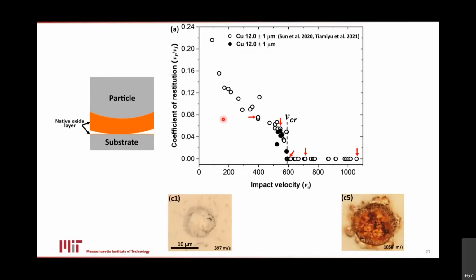Now let's go to the other side of this diagram. Here's what it looks like if I do this impact, but the particle bounces away and I've just dented the substrate. You can see we've made a crater, but we haven't got any change in the oxide. It's just a clean, well-prepared substrate; there's no oxide going on. So this is full oxide, this is no oxide. Now we can go to the region in the middle and start to explore it. In between, we see exactly what we were expecting: in the range where jetting is starting to happen, first of all, you'll see evidence of those jets starting to form around the periphery of the particle.